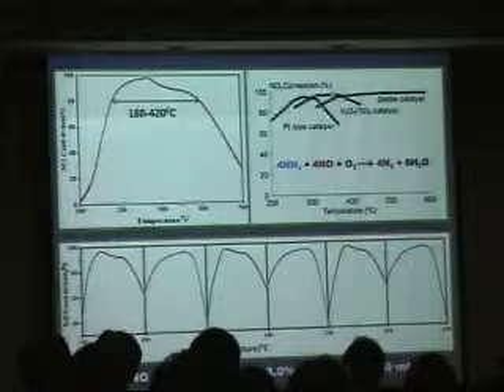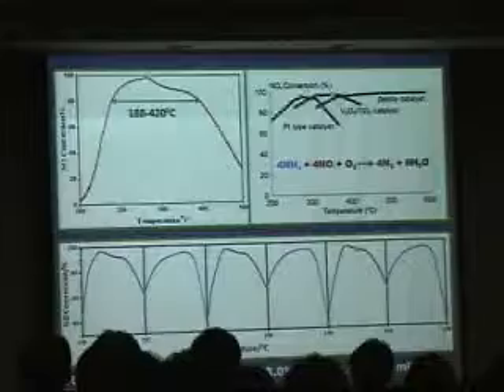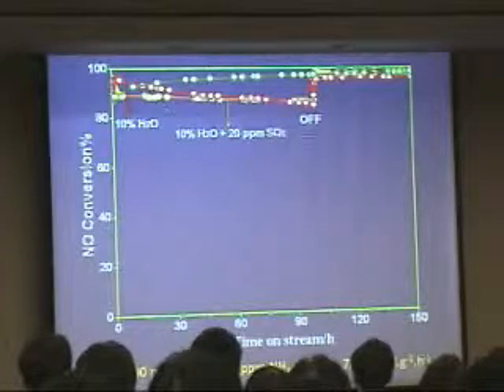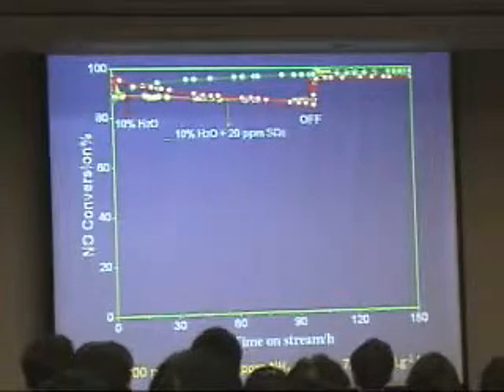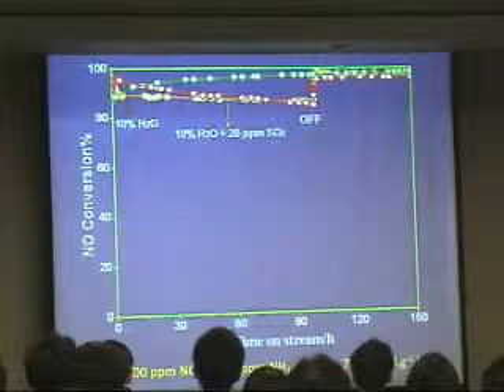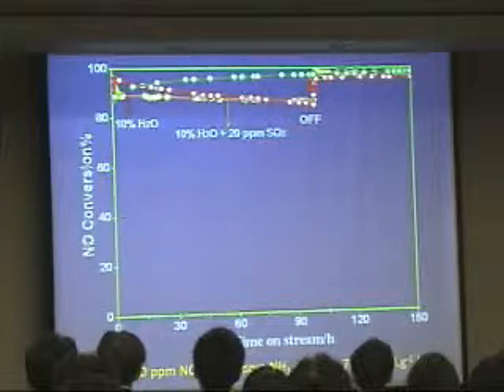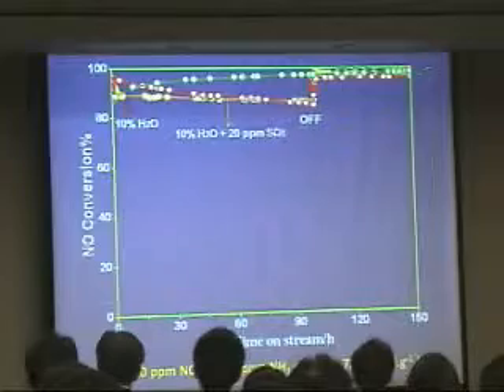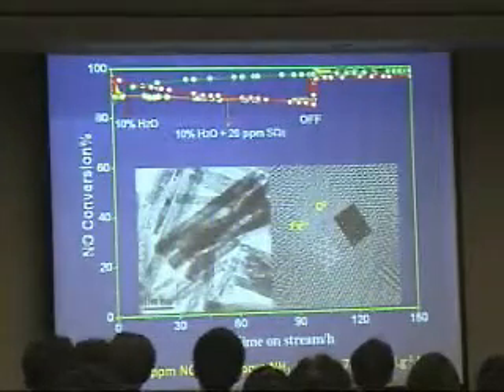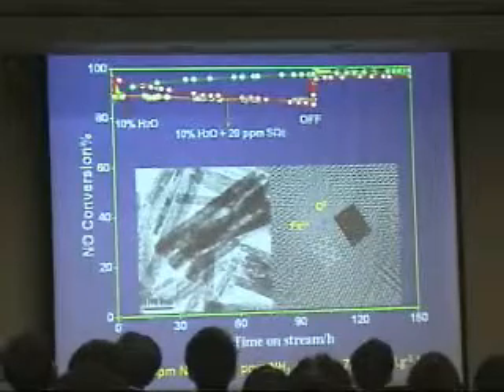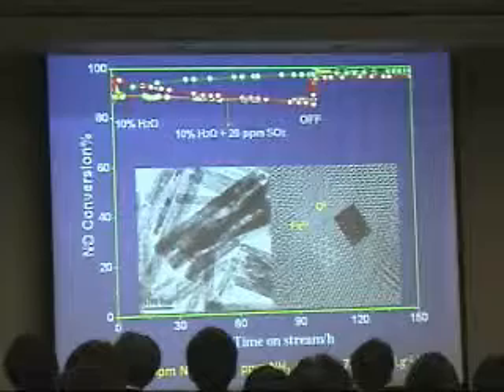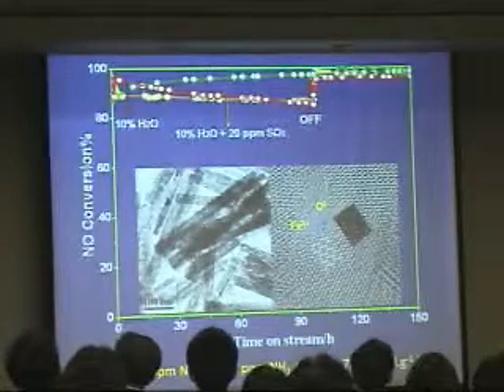And we ran a long-term stability test to see the potential application of this very cheap material. We tested for more than 100 hours with real DeNOx gas conditions. We find the sulfur oxide and also water do lower the activity, but it is only a reversible process, not an irreversible process. So after the test, we take the sample out to see the structure. It is still the rod-shaped structure, and the surface is also exposing the iron cations and the oxygen anions on the surface.